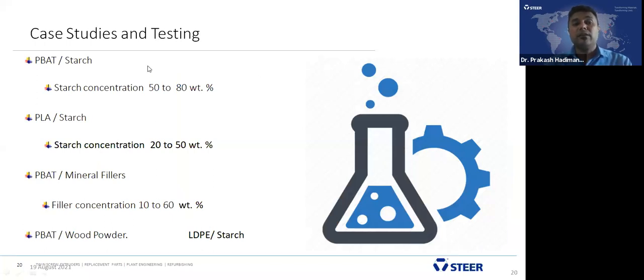In today's case studies, we did many combinations. The first combination is PBAT and starch. We added starch up to 50 to 80 weight% with the PBAT. Second is PLA and starch, where the starch concentration we added is 20 to 50 weight%.